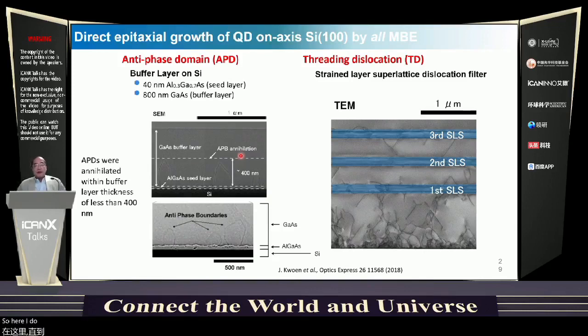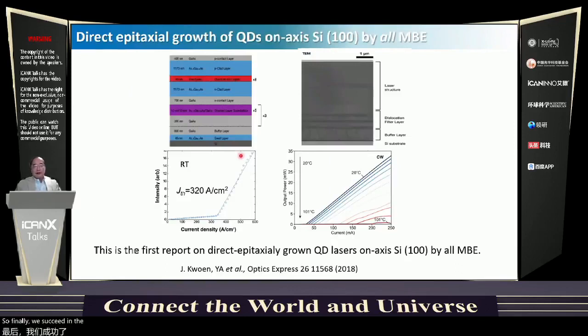So here the anti-phase domain effect can be avoided or suppressed by growing buffer layers on silicon very carefully. And also threading dislocation can be suppressed by using strained layer superlattices, dislocation filters, and so on. So finally, we succeeded in the first direct epitaxially grown quantum dot lasers on on-axis silicon 100 substrate by all MBE. We don't need to use patterned substrate or a template grown by MOCVD and so on.